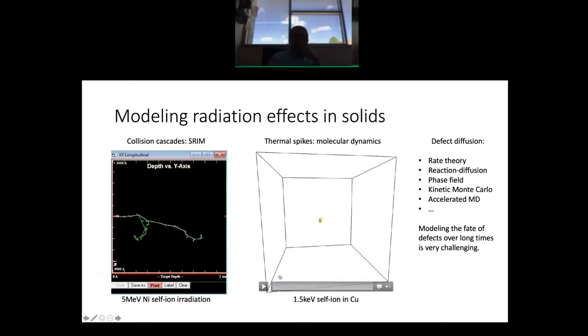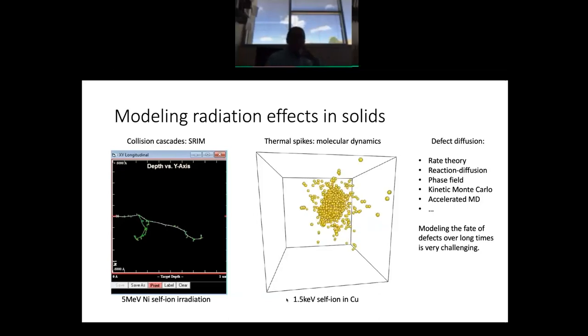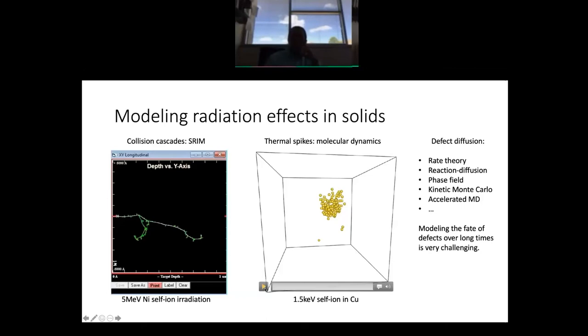When it comes to thermal spikes, at this point, the energy dissipation that's going on is so localized that you can't really use the binary collision approximation anymore. So instead, we use molecular dynamics. This is an example of a simulation of a 1.5 kiloelectron volt collision cascade occurring in copper, right? So FCC copper. What I've done in this simulation is I've taken all of the atoms that are perfect face-centered cubic atoms, and I've removed them. I've suppressed them just for the sake of visualization. And all I'm showing you here are the high energy atoms that are in the thermal spike itself.